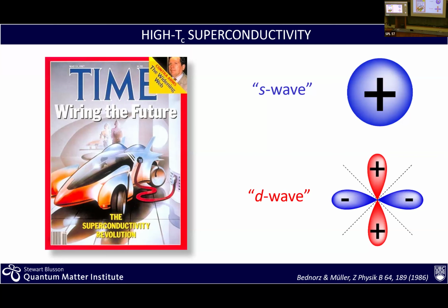So the conventional, more typical kind of superconductivity is so-called S-wave, where that pairing is fully isotropic in space. But the alternative proposal would be that perhaps in this case we're looking at a gap which is D-wave in nature, where you have regions with very strong pairing. These are actually the directions where the copper-oxygen bonds are aligned in the material, and directions where instead the pairing goes to zero. This is where the node, so the zero in the pairing amplitude, is located.